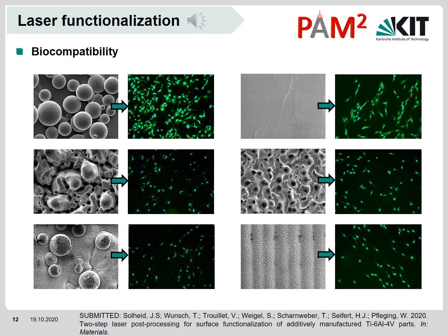Finally, the cell growth analysis indicated that independently from the process to which the Ti64 samples were submitted, no increase in the surface toxicity was observed, and the cells were capable of attaching to the part's surface, although in an arbitrary manner.